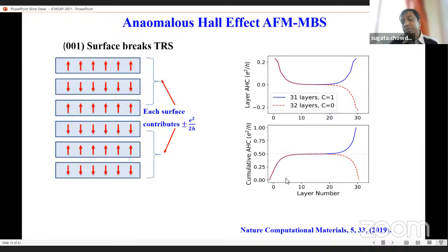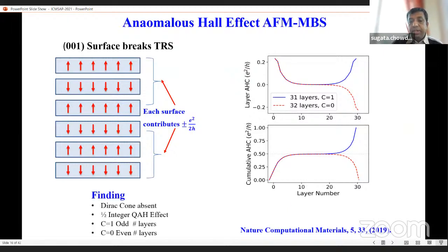If you notice, the transport properties depend on the layer number. Here the blue line shows the odd layer and the red line shows the even layer. So the Dirac cone is absent and it is a half-integer quantum anomalous Hall effect. C equals 1 when it is odd, which means it is in the ferromagnetic state, and the Chern number C is 0 when it is an even number of layers of the MBS system.